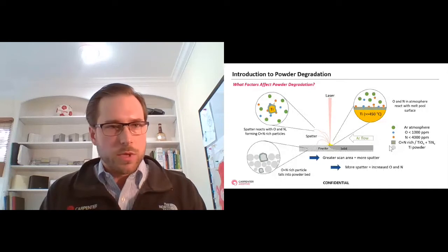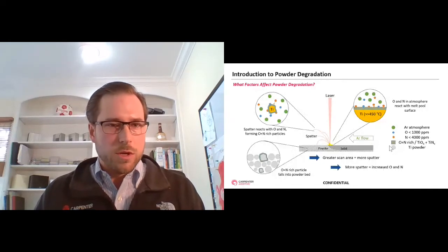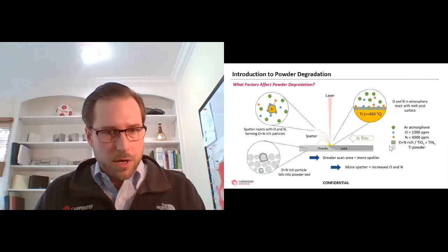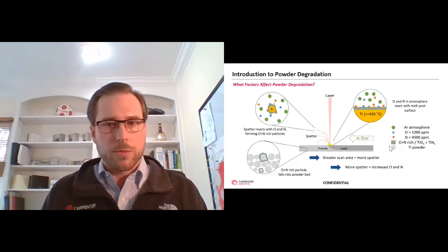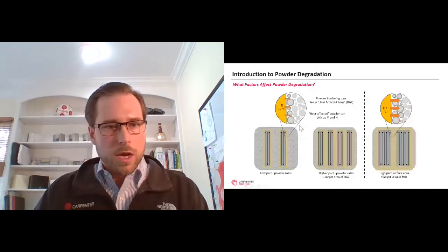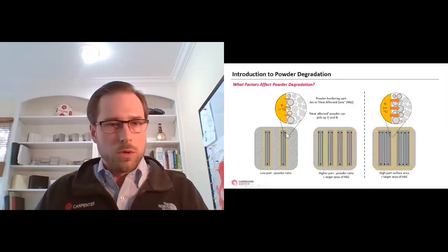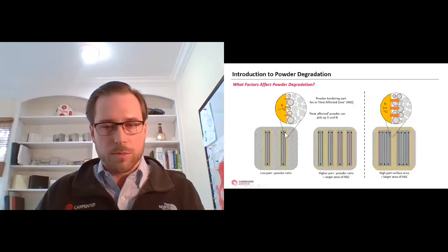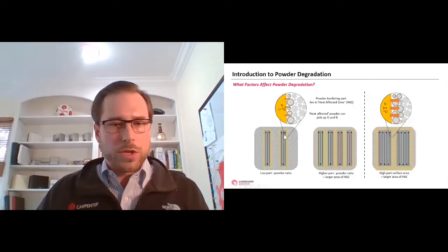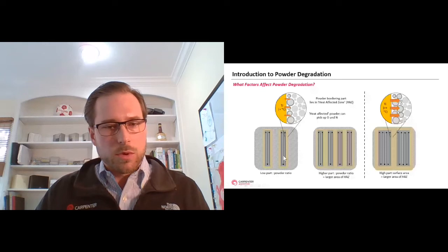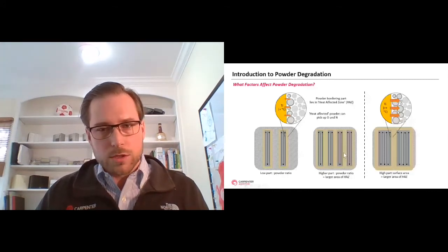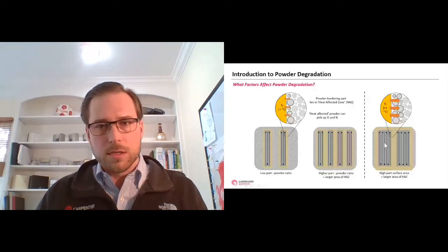The second mechanism that we see is a heat affected zone. So the powder surrounding the part, we see oxygen pick up there, because although it's not being heated up to a melting temperature, it's heating up enough to start absorbing oxygen out of the atmosphere. And even if you have a really low level of oxygen inside your machine, you're still going to see some level of pickup and some level of degradation. And what this slide is demonstrating is that scan area, so more or less parts, is going to impact your amount of powder that's in your heat affected zone, as well as the size of your parts and the latent heat that's in them.